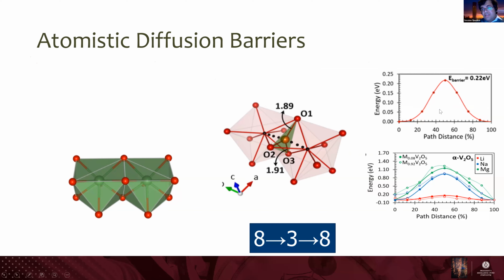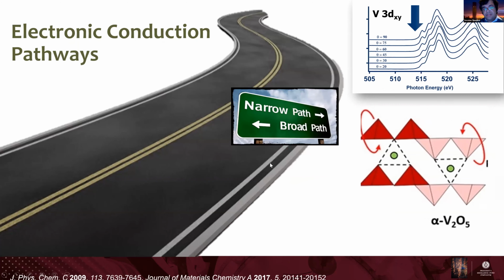And for lithium, this is not completely impossible. You can see for other ions like magnesium, this becomes really, really challenging. Almost an eV worth of energy is required to squeeze the magnesium across these barriers.